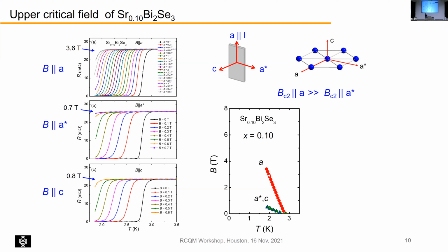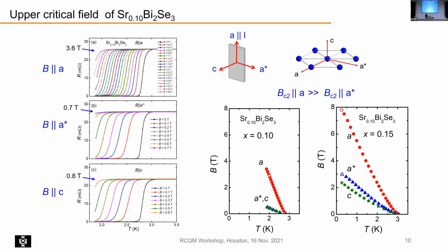So we said, okay, that's one sample. Let's look at another sample. We made a sample with x = 0.15, and we measured also down to much lower temperatures, and we find the same. We find a very large anisotropy between A and A star. This is 8 Tesla, and this is like 3 Tesla. So this is really a large effect.